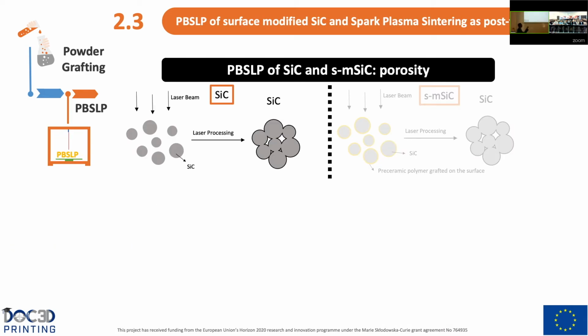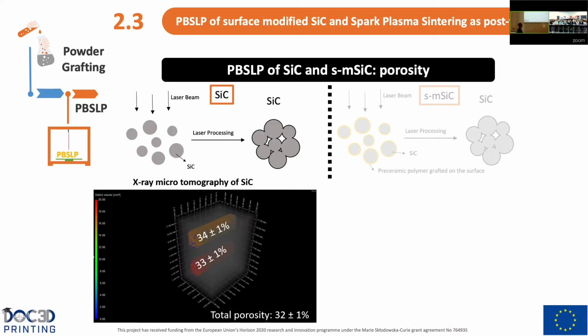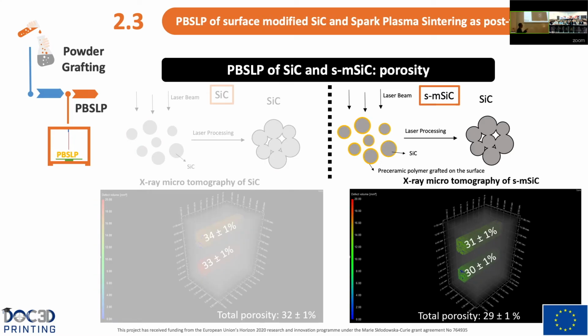Regarding the porosity of the silicon carbide after the process, by performing X-ray microtomography, we are obtaining a total porosity of 32%, compared with interior values of regions of this part, 33 and 34%, very close values. And in comparison, with the surface modified silicon carbide, we obtain a total porosity of 29%, with interior volumes of 30 and 31%.